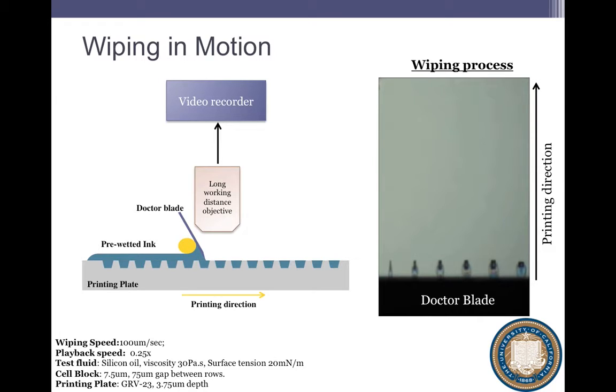It turns out that as the doctor blade passes each cell, ink wets the back of the doctor blade and rides up. And then once it passes the doctor blade, it's in a non-equilibrium condition, and a substantial fraction of that ink gets redeposited back down again behind each cell. So what that means is two bad things have happened. First, while I was passing the cell, I sucked ink out of the cell. So my cell, which was 100% full, is now less than 100% full. And second, it deposited in a region that I expected it to be clean. So this is bad.